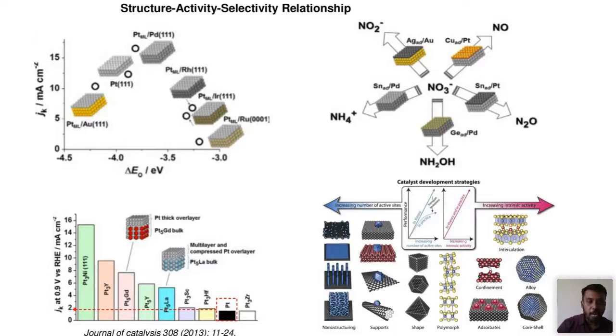For instance, if you have a platinum gold alloy, it produces only 5 milliampere per centimeter square current density in oxygen reduction reaction. Whereas if you have a platinum palladium alloy with 111 phase, then it produces 15 milliampere per centimeter square. So instead of forming an alloy with gold, if you form an alloy with Pd, it is good for oxygen reduction reaction. Similarly, when you form platinum rhodium, platinum iridium, platinum ruthenium, the activity trend decreases. So based on these trends, you can form the alloys, and based on the structure, you can control the activity and selectivity.